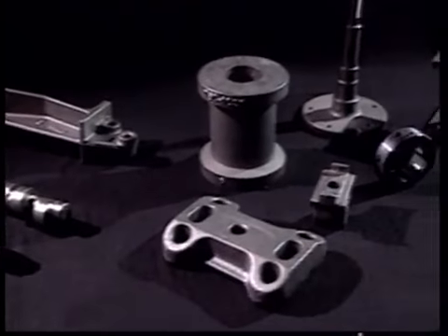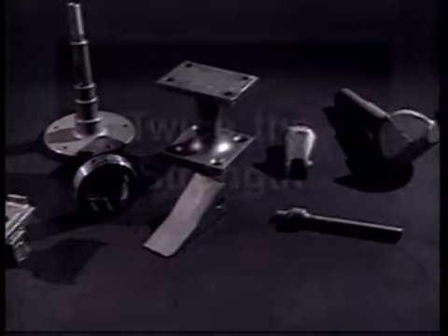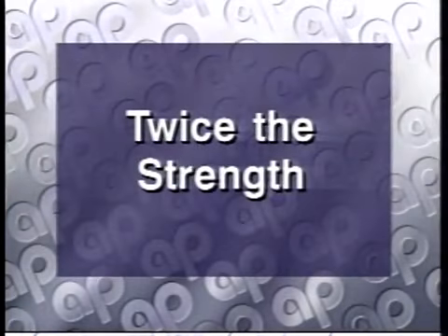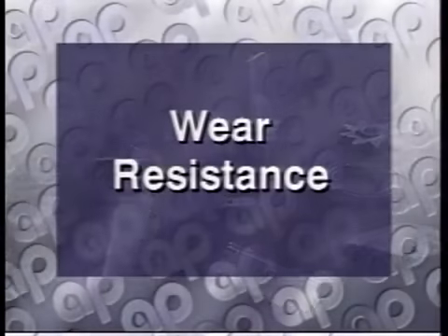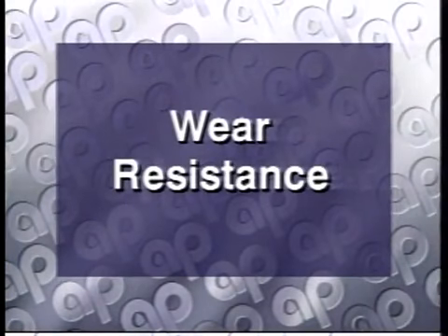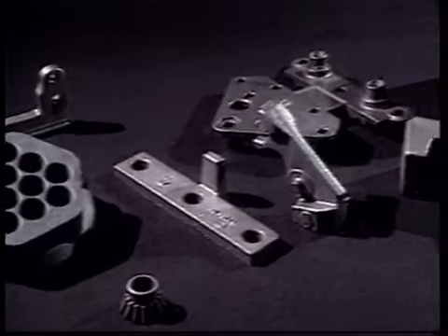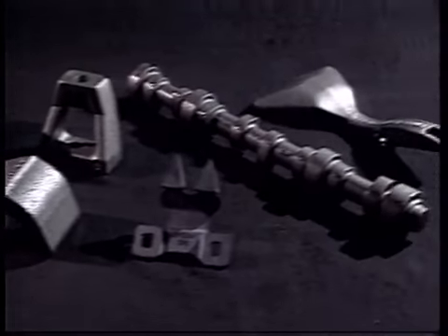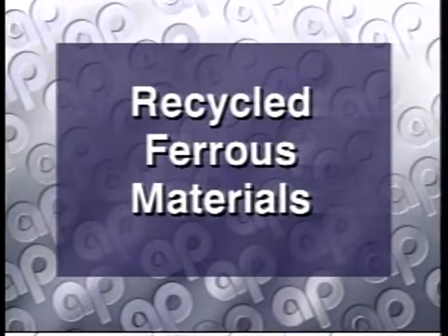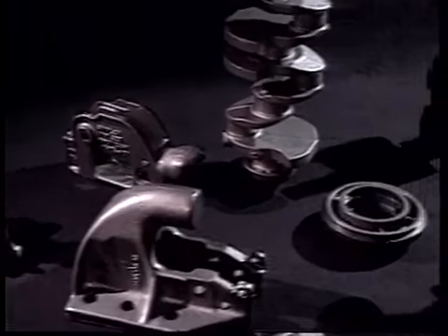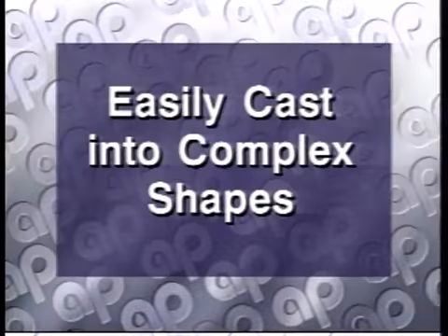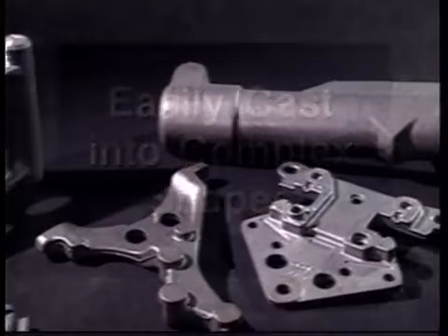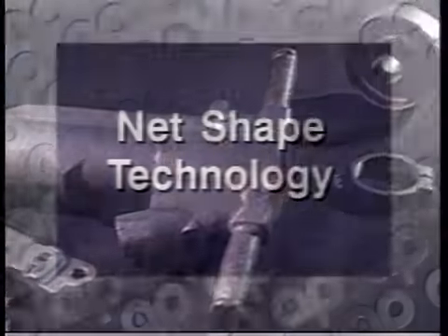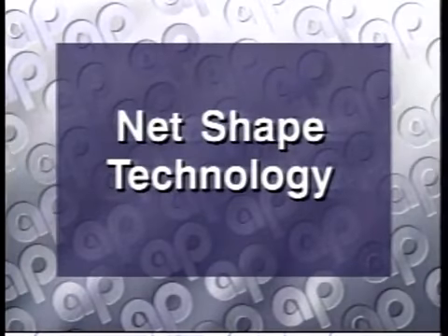Compared with conventional grades of ductile iron, ADI has over twice the strength for a given level of ductility. ADI has remarkable wear resistance for a given hardness level when compared with other materials. The ductile iron casting process uses recycled ferrous materials. Ductile iron can be easily cast into complex shapes. Therefore, ductile iron is a near net shape technology.